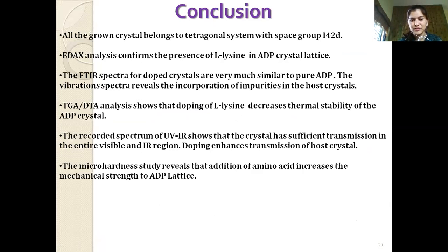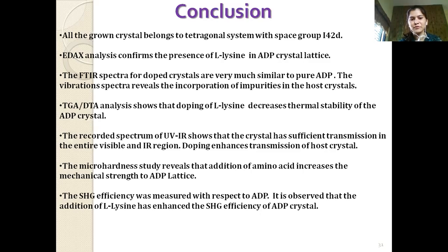The micro hardness test confirms the increase of mechanical strength of ADP due to doping, and SHG efficiency was also measured, which shows that the NLO coefficient increases due to the presence of L-lysine in the ADP crystal.